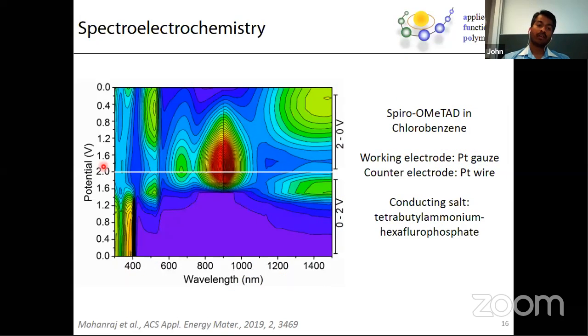So we went down from 2 volt down to 0 volt again. You could see, when we drift back from 2 volt to around 1.2 volt, we again start to see the features that we saw before around 520 nanometer in here. At the same time, the intensity of these features starts to decrease. And concomitantly, we see also the generation of new features that we saw before. So basically, we are just playing here with potential. We oxidized and then reduced, and you can keep on doing that as many times as you wish.